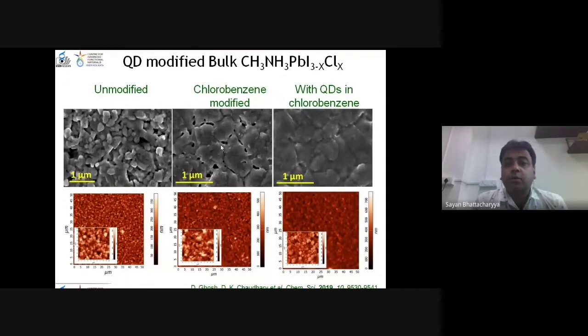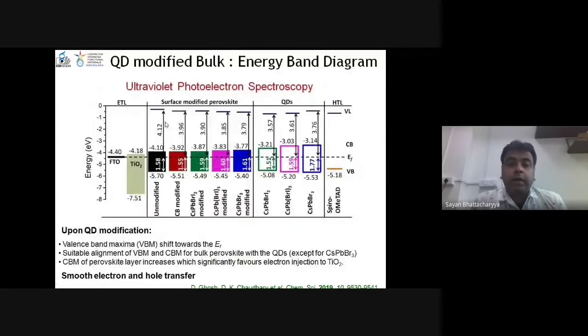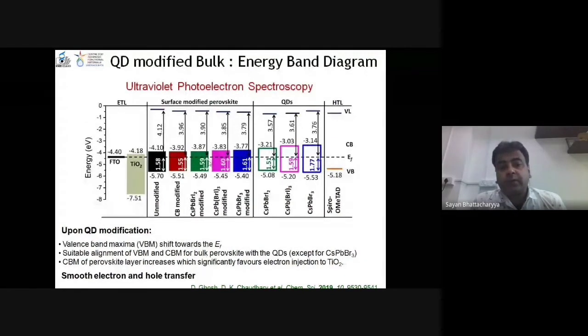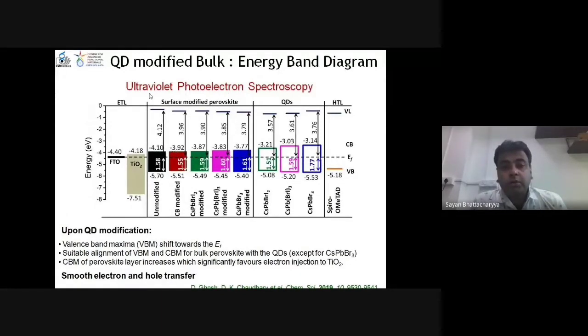This is not modified, this is the chlorobenzene, and this is with quantum dots. You see the roughness has been reduced a lot. And this is atomic force microscopy. You see in the same way that roughness has been reduced. Of course, it is needless to say that the electron transfer and hole transfer depend a lot on the band alignments, whether the bands are suitable or not. This is by ultraviolet photoelectron spectroscopy. As we deposit the quantum dots on the films, we see that the band gap changes, as well as the conduction band and valence band levels. This energy also changes. It has to be such that the electron goes to TiO2 and the holes go to the valence band, to the hole transporting material on the right.